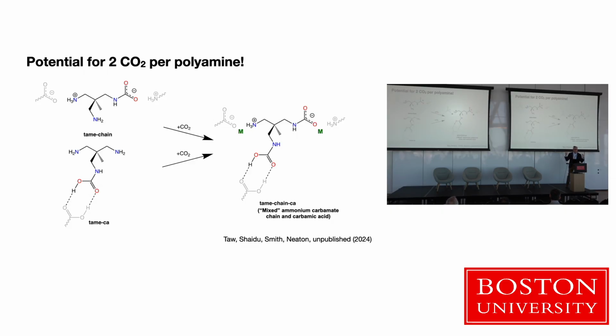And the amine ligands themselves, the linkers themselves, have a lot of low energy degrees of freedom. So relaxing a structure like that with conventional methods is pretty hard, and also pretty hard to convince yourself that you're in a ground state, in a global minimum. And so basically what we did, to cut the long story short, is we used an MLIP and simulated annealing to essentially find the global minimum of one of these structures.